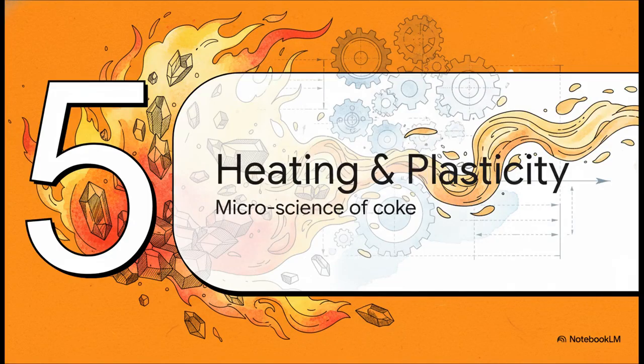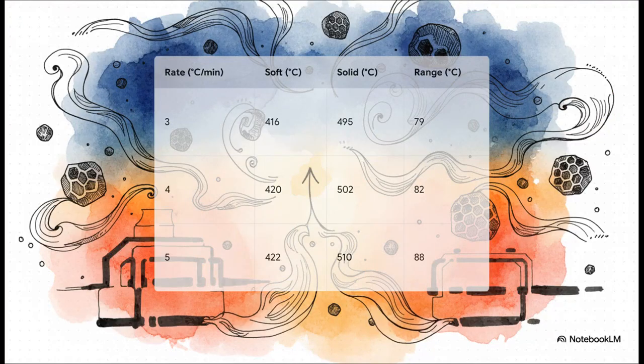All right, Section 5, Heating Rates and Plasticity, the microscience of strong coke. Here's where the real microscience kicks in. The magic isn't just in what temperature we hit, it's how fast we get there. Data from a Gieseler plastometer, which is a tool that tests fluidity, reveals something remarkable. By increasing the heating rate by just 2 degrees per minute, moving from 3 degrees to 5 degrees per minute, we actually delay the solidification temperature by up to 15 degrees. This drastically widens the plastic range of the coal blend.